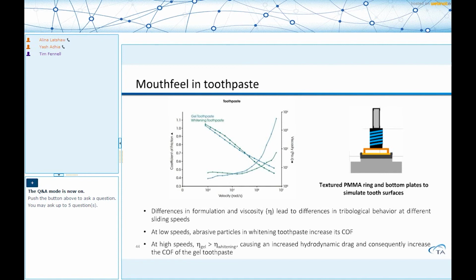So if you look at the viscosity of these two materials, at low speeds, they're more or less comparable, but as you go to higher speeds, the gel toothpaste doesn't shear thin as much. So it has a higher viscosity. And again, when you go into the hydrodynamic drag side of things, a higher viscosity is going to impede the motion more.